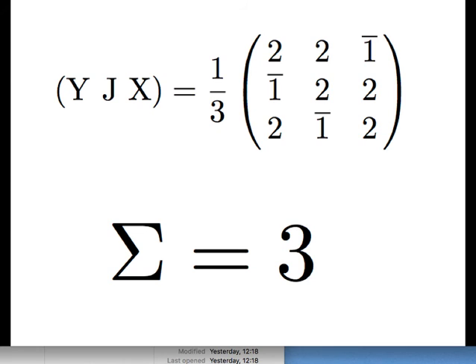Everyone happy with that? In a very short time, we've covered an incredible amount of knowledge about boundaries. You learned for the first time that the structure of a boundary consists of dislocations, and you can see those dislocations in a transmission electron microscope and work out their Burgers vectors. You can estimate the spacing you should see between the dislocations given a Burgers vector, and you can work out the interfacial energy per unit area for small values of theta. But at certain misorientations, you will get coincidence between the two lattices, and at those misorientations the interfacial energy, diffusion coefficient, etc., will be dramatically affected.